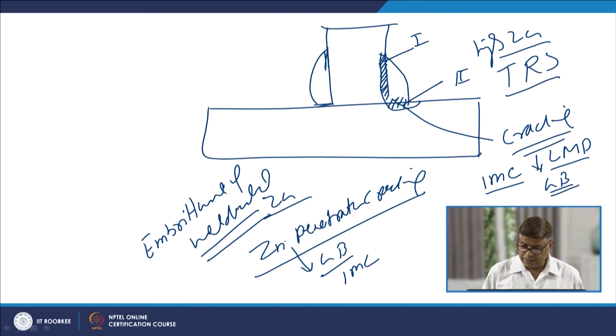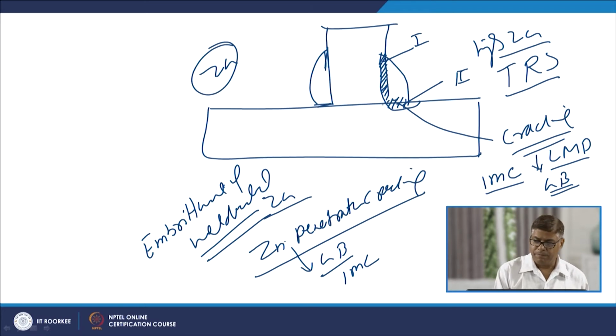This kind of the cracking tendency is found more in the regions where the zinc concentration is more, which is especially the root of the weld metal, where zinc tends to segregate, or zinc is found in the greater quantity.